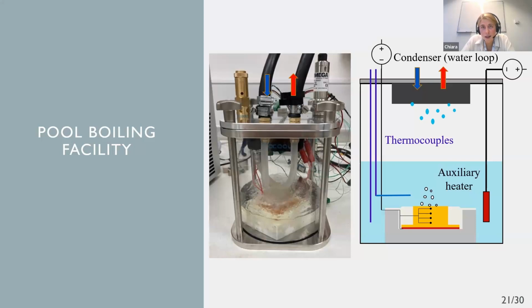Yes, there will be practical limitations of the liquid, again, related to the size, the compactness and the weight of the system, but also on the boundary conditions, meaning the temperature at which the system is installed. In our lab, there's an ambient temperature, and we can control the condenser side, the top plate, very easily. But what happens if the external condition varies, and can we integrate it in a system where we can exploit colder temperatures outside or close to the skin of the aircraft? These are all open questions that are very interesting and still need to be investigated by my group.